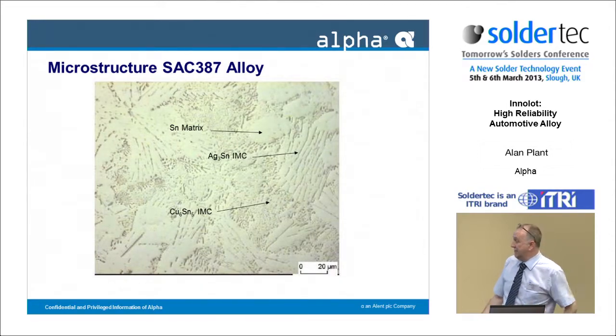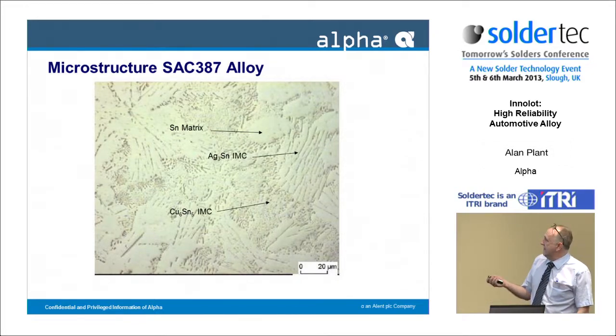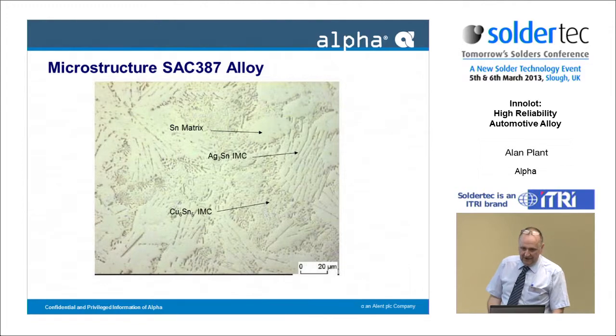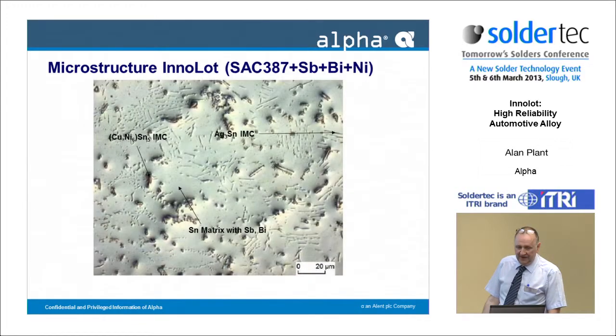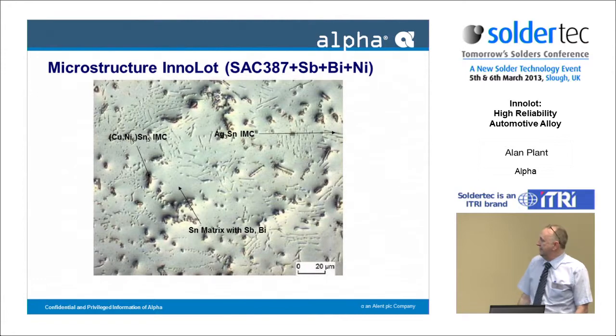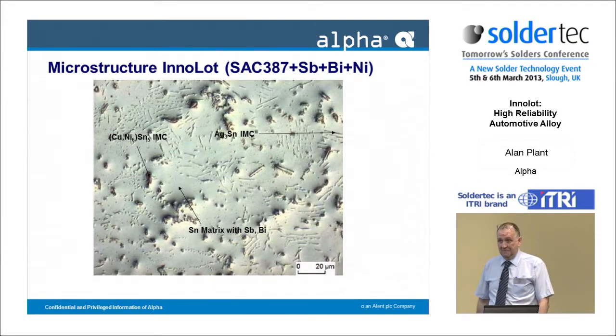And again, as I said before, don't be last up because you've all seen this before. So, nice tin matrix, tin silver intermetallic compound, and copper tin intermetallic compound. Having made it a 6-part alloy, this is what the consortia did to it. You've got your tin matrix now with your antimony and bismuth solid solution strengthening. You've still got your tin silver intermetallic compound, but you've now got the copper nickel tin intermetallic compounds in there, giving you your dispersion hardening.